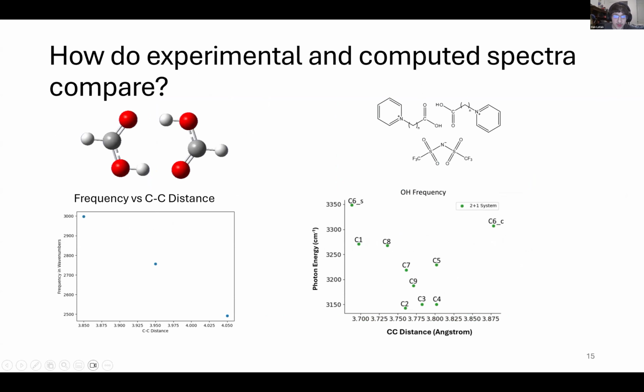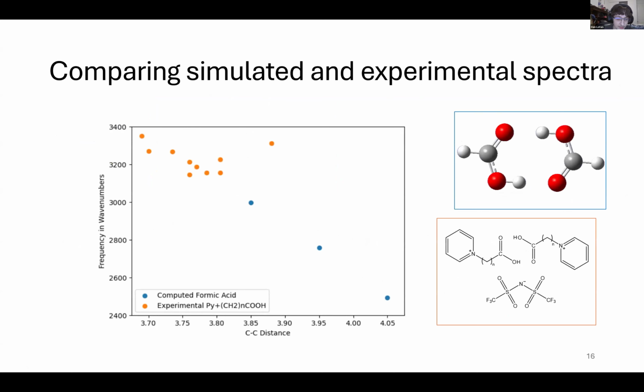So I showed you before what the experimental values look like. Unfortunately, we don't really expect this to match one-to-one. These are different molecules after all, and the actual molecule that was measured is a lot more complicated. However, if you take these two plots and put them on the same graph, it's kind of remarkable how well of a relation this has. From what's been collected so far, it definitely looks like the CC distance is what's legitimately causing this, because I basically took all the other factors out that could have affected it.